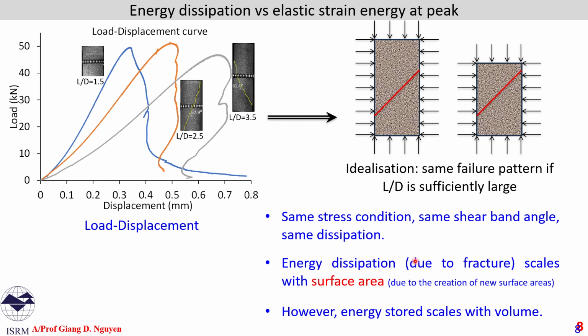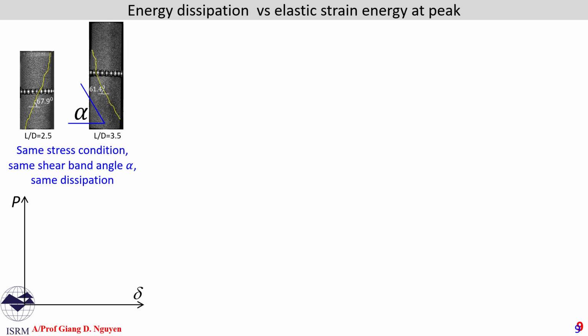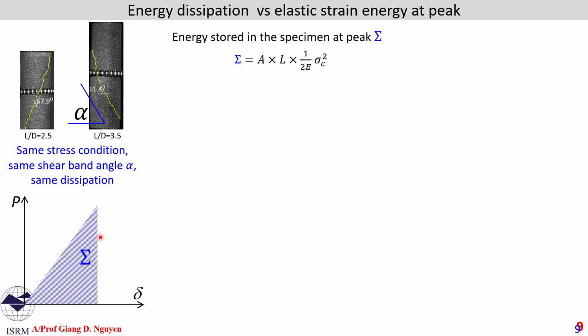The area under this curve represents the energy stored in the specimen, and the stored energy scales with the volume. So the larger the specimen, the larger the amount of strain energy stored at peak. If we look at these two cases as an example, we plot the load against displacement. At peak, this specimen is storing some amount of energy that scales with the volume: A, the cross-section area, times the length, and one half over E, sigma c squared, with sigma c being the compressive strength, is the strain energy, that is, energy per unit volume.